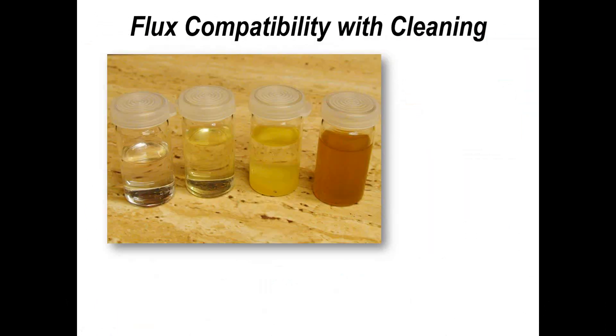The first thing you have to do when setting up any cleaning process is to determine that your chosen flux can be removed from the printed circuit board by your chosen cleaning chemistry. We don't have to worry about the efficiency or performance of the cleaner to start off with. What we're interested in is whether the material is soluble. If the residues are soluble in your chosen cleaning chemistry, it's going to make it a lot easier to remove from the printed circuit board.